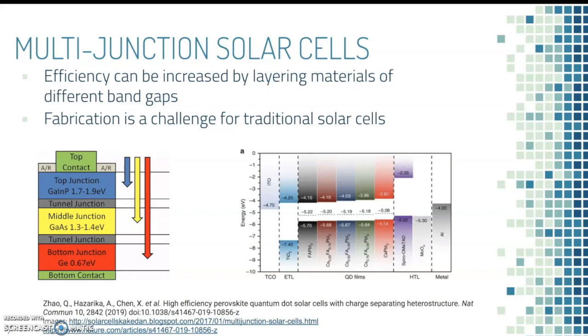They are suspended in solution, so there is no crystal lattice that needs to be matched. Films of quantum dots can simply be deposited on top of each other to create a multi-junction cell. Finding materials with optimal bandgaps is also easy because changing the size of the bandgap of a quantum dot is as simple as changing its size. Efficiency of a multi-junction solar cell can reach 50% for 2 layers with optimally chosen bandgaps.